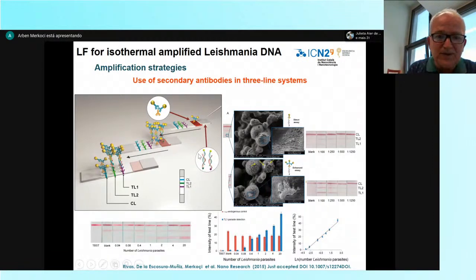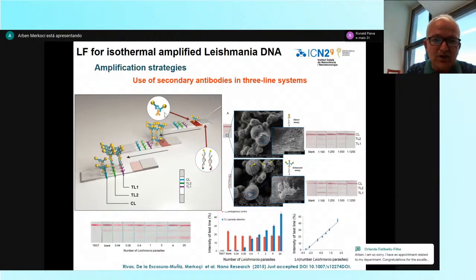In fact, we use this amplified DNA that was introduced into the paper, and by using some antibodies that were connected with peptides, we are able to detect directly this amplified DNA. And of course, by using some secondary antibodies modified with gold nanoparticles, we are able to amplify further the sensitivity of the signal coming from these gold nanoparticles.